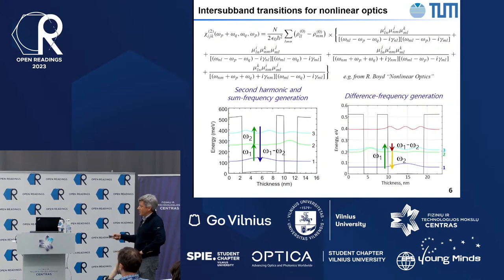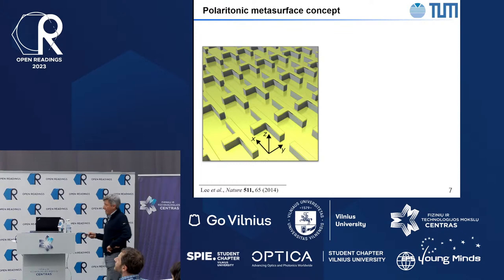So this is an example of the design of quantum wells for second harmonic generation. And this is a structure that would have strong nonlinear response at difference frequency generation. With this alone, we can already boost the nonlinearity by maybe 10,000 times compared to that of traditional nonlinear crystals. But we can go further. We could then place these quantum wells inside of nanoresonators and further boost the nonlinear response by playing with the electromagnetic properties of our metasurface. This is something that people have done in the past with other metasurfaces using bulk existing nonlinear materials. Now we could use our nonlinear materials and squeeze them in and really produce record high nonlinear response.